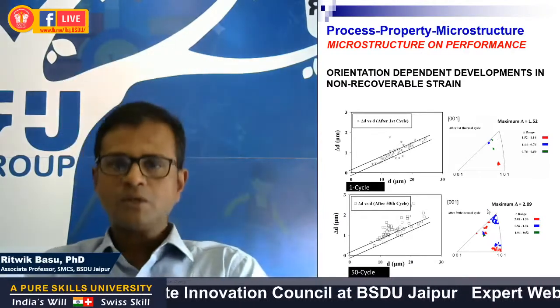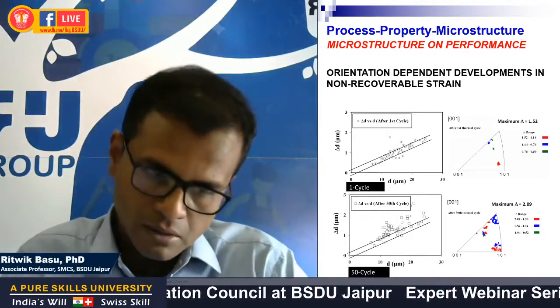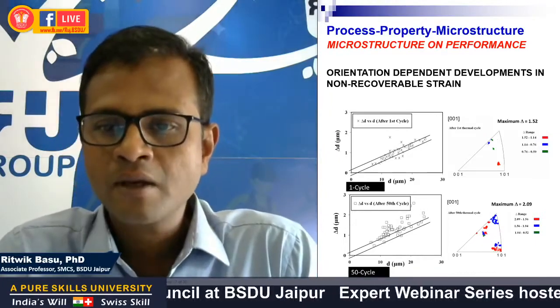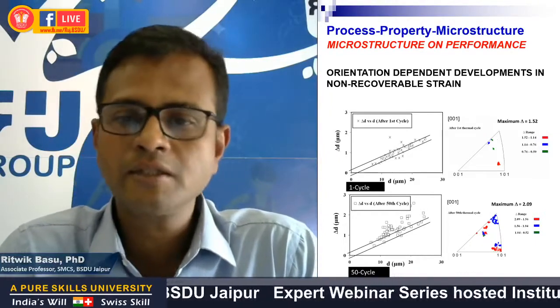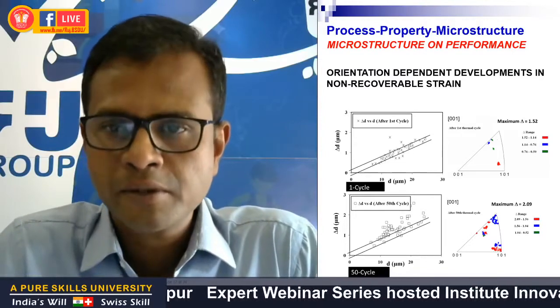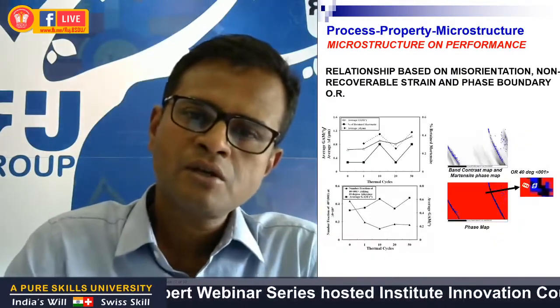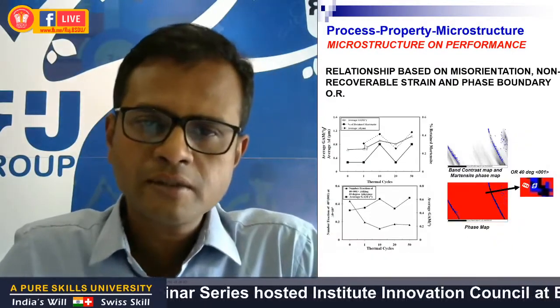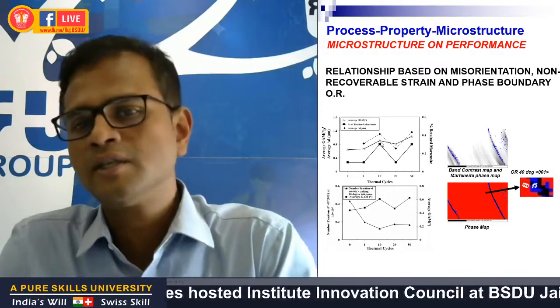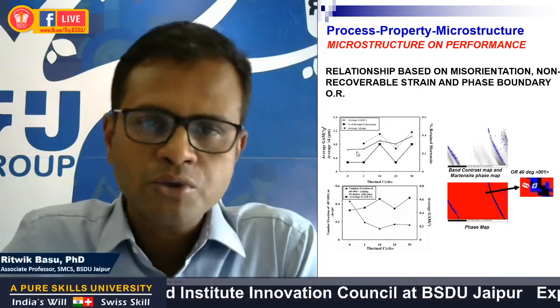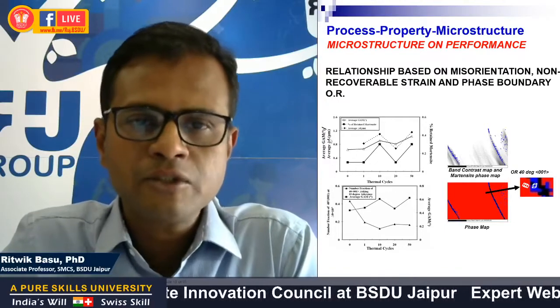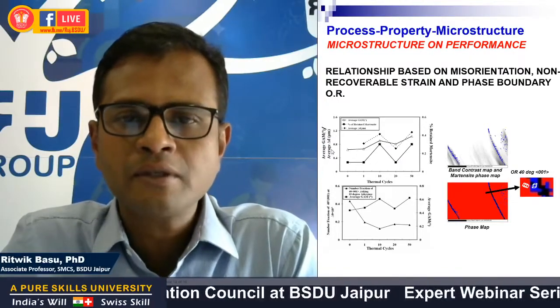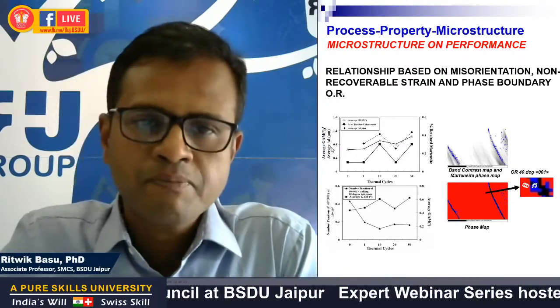So the second conclusion from this study was that the irreversible strain, this quantity delta D, is very much orientation sensitive. We also found that the increase or decrease in the delta D average coincided with similar or identical changes in the average misorientation and the fraction of retained martensite.